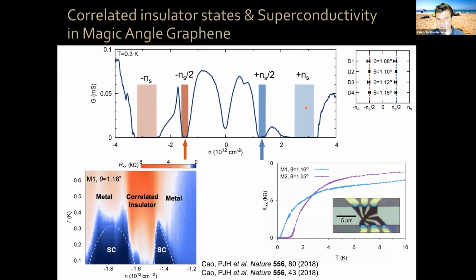So, and then what my group discovered 3 years ago now is that when you populate, with the chemical potential, those flat bands, you can have unusual correlated insulator states at fractional fillings of those flat bands. And if you dope a little bit away electrostatically from those fractional fillings, you get superconducting domes, okay? Magic angle twisted bilayer graphene is an electrically tunable superconductor where you can have various types of superconducting domes in the system. This all happens for a small range of twist angles around 1.1 degrees, something between 1 and 1.2, maybe 0.9 to 1.3 degrees, this type of physics.